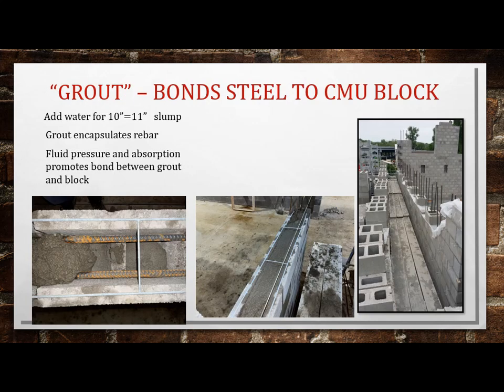So grout bonds the steel to the CMU block. Grout is placed very wet, soupy, like a 10 to 11 inch slump. The reason for that is the grout is pumped into the block, into the open cells, and the block is dry, so the block absorbs the moisture out of the wet grout. And so that's the bond strength.